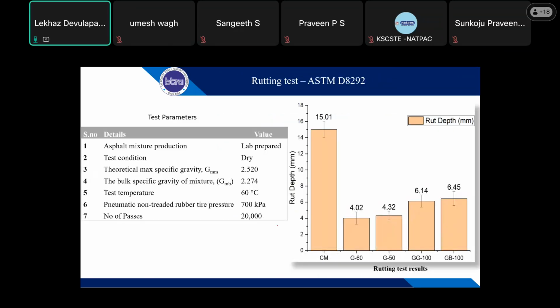And these are the results from our research. We conducted this in a dry condition at a 60-degree temperature, with a tire pressure of 700 kPa applied on the pavement, and we went up to 20,000 passes. For the control mix we got 15.01 of rut after 20,000 cycles. When we have the geogrid reinforcement in the pavement, we have a rut of 4 and 4.32, and for glass grid it was 6 and 6.45. We can see that the rut resistance has been considerably improved by placing a geogrid.